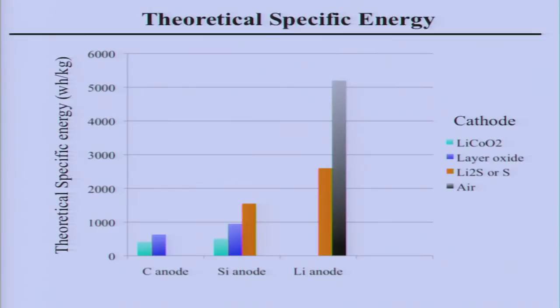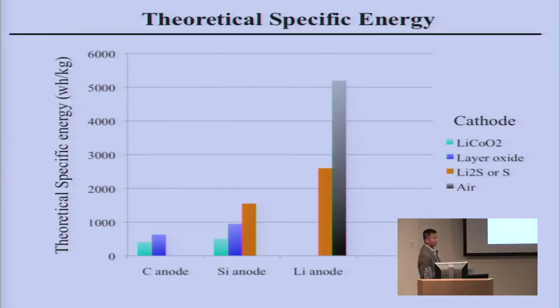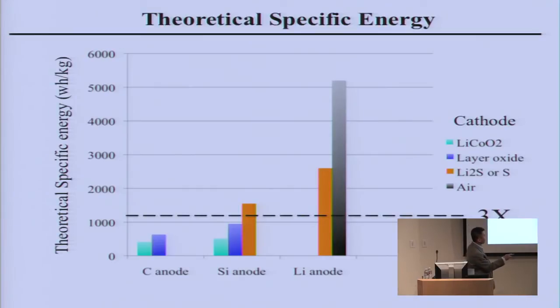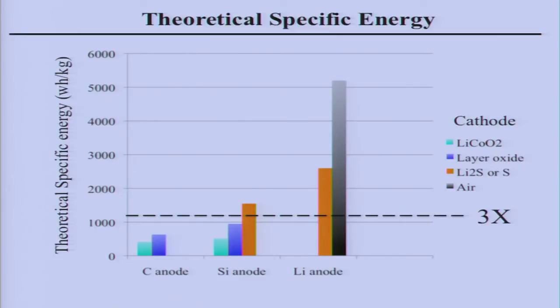There are challenges. But let's look at where the potential of these materials can take the energy density. This is energy per weight, based on these active materials alone, how many electrons they can store. I compare current technology using graphite carbon with these different cathodes. This is what graphite can give you. For a fair comparison, it's active material with active material. This is the 3x line. Silicon with lithium sulfide will allow you to get to 3x. And if you are greedier, lithium metal and sulfur gives you 6x. We haven't got there yet because there are too many materials problems inside. We have not been able to realize the full potential of these new battery chemistries based on the lithium system.